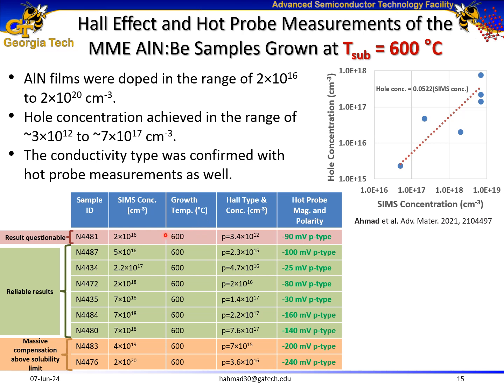Later, I grew beryllium-doped aluminum nitride samples at a substrate temperature of 600 degrees C at different beryllium doping levels. Beryllium doping levels where the Hall results were questionable, beryllium doping levels where we see massive compensation, and beryllium doping levels where we achieve reliable results in the range of 10 to the power of 15 to mid 10 to the power of 17 per centimeter cube, resulting in activation efficiency of approximately 5%.